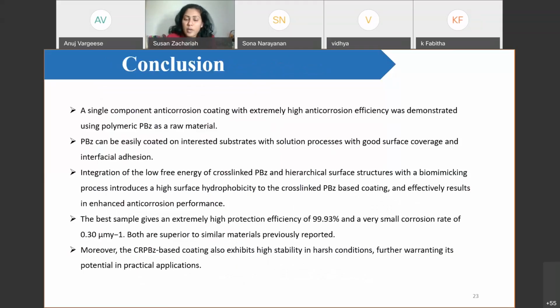In the conclusion of this first work, we have made a single component anti-corrosion coating with high protection efficiency, and here we have obtained a protection efficiency of 99.93%. We also used a nature-based biomimic Lotus leaf to get this pattern. Moreover, this cross-linked PBz based coating also exhibits high stability in harsh conditions, further validating its potential applications.